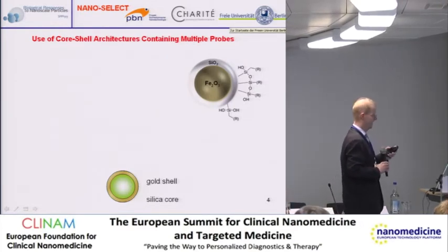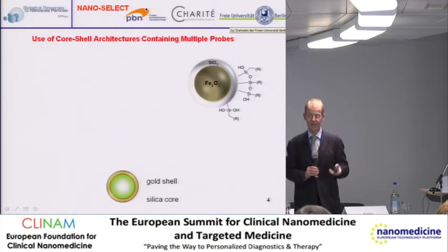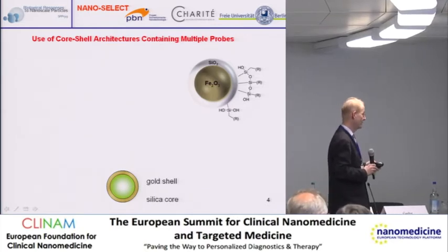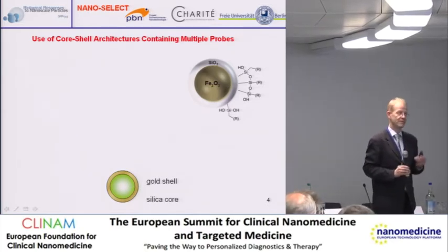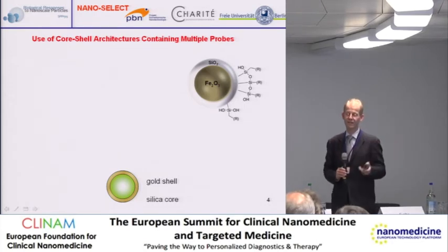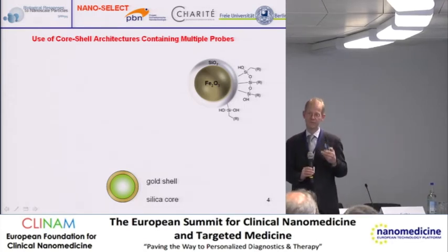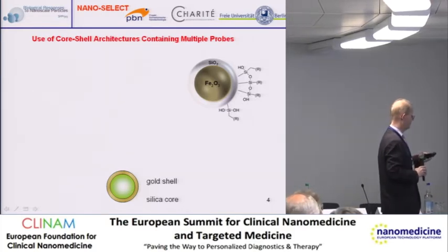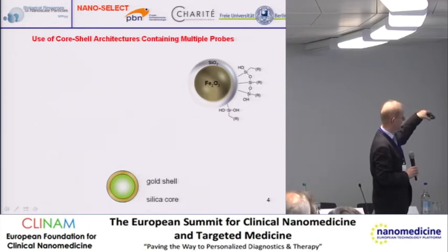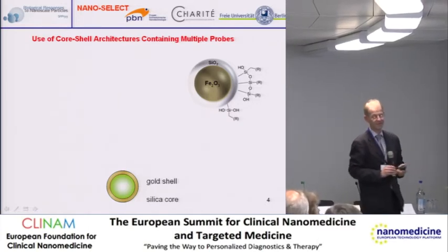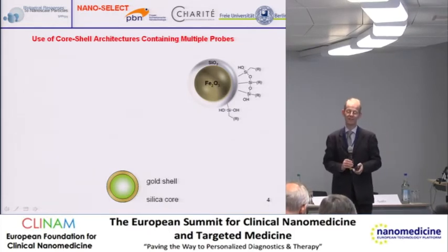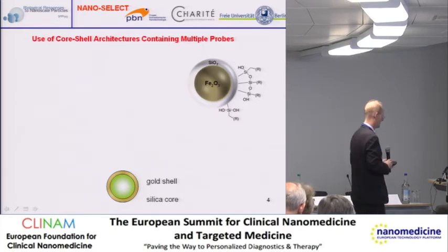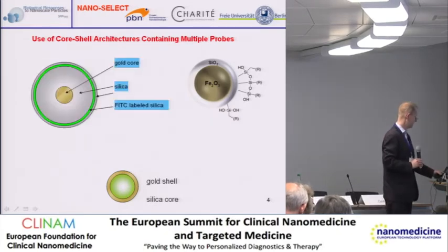They are either silica particles or iron oxide particles, where core shell architectures play a crucial role, because these allow us to substructure the particles to include, for example, molecular probes or possibilities for distinct probing of the nanoparticles, and also the variation of the surface material allows us to covalently bind functionalizations that are of importance for the interaction with the biological media.